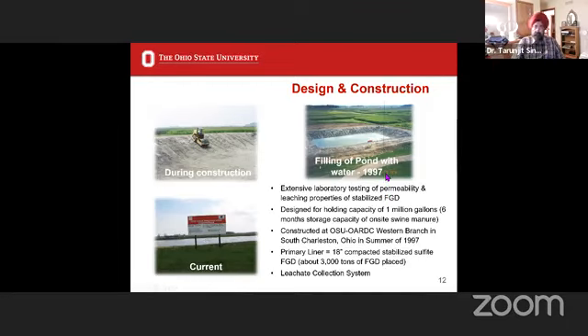This was filled first with pond water, regular water. After we were sure that the permeability was suitable, it was filled. This is a swine farm, and so it was then filled with swine manure, where it is currently still being used. The primary liner is 18 inches of compacted stabilized sulfite FGD material, to which we added fly ash. About 3,000 tons were placed.